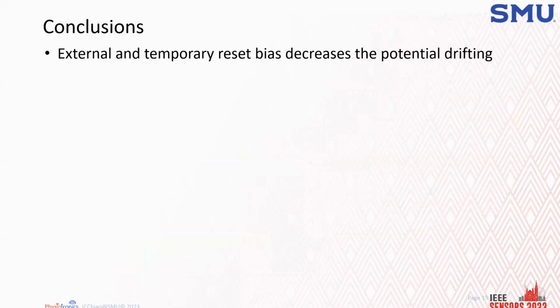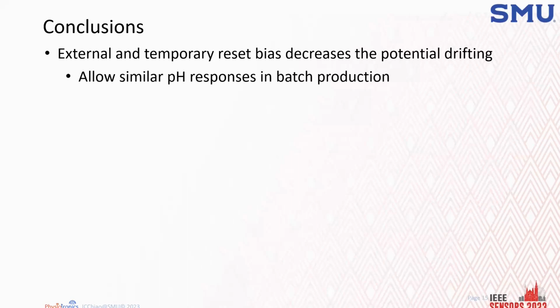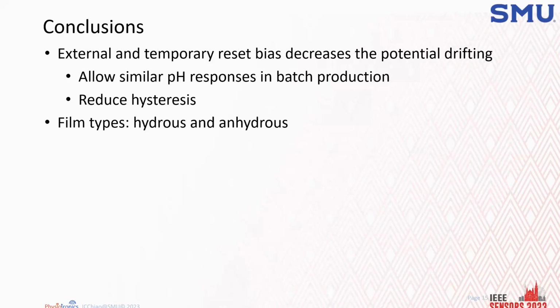So to conclude my talk, we found that by externally applying a 2 minute reset bias, you can improve the pH sensor and improve the phenomenon of potential drifting. And once this potential drifting issue is fixed, we can make sure that all the pH responses in batch production will be the same, and it also reduces the hysteresis. And this guarantees that we can use the sensor for long-term measurement without calibration.